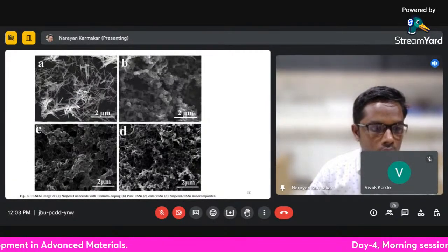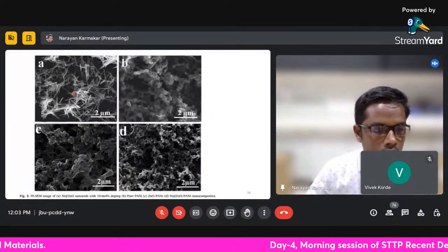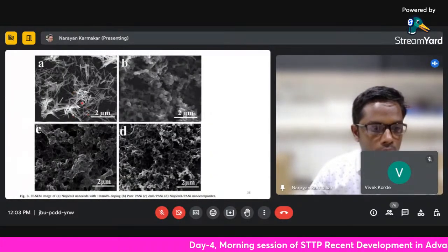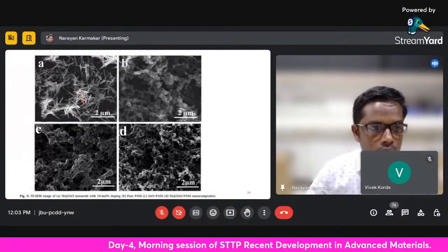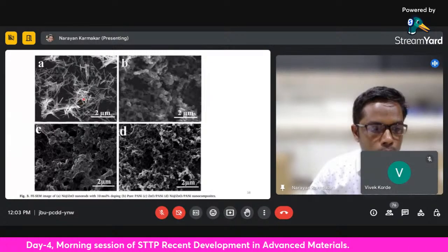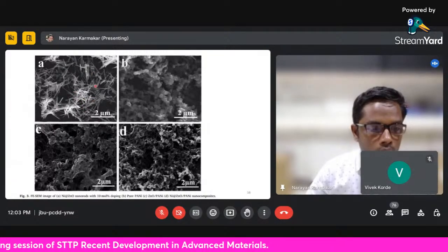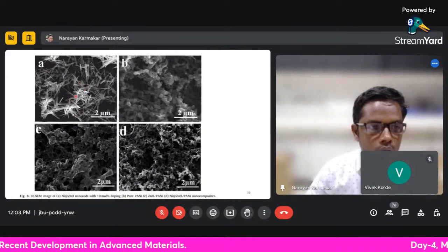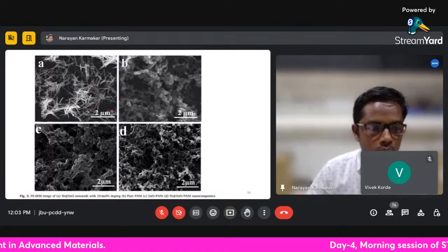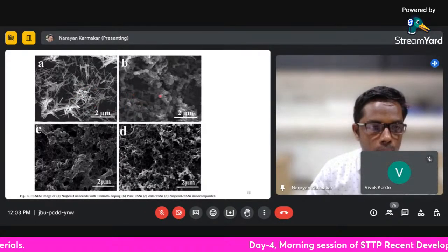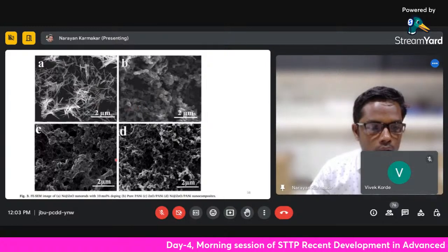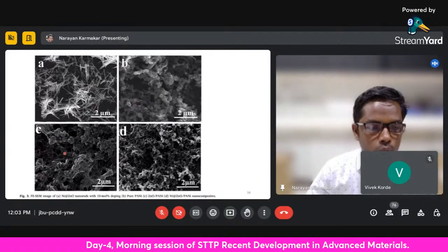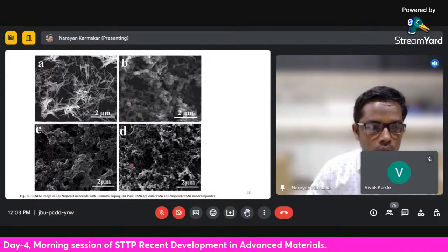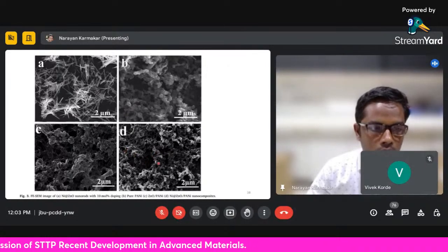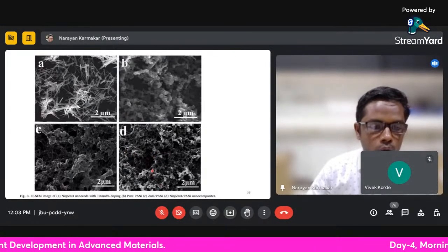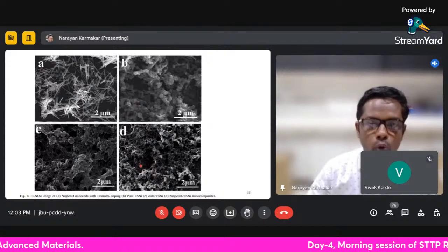So this is the image of this nickel-doped ZnO nanorods with 10 mol% doping, where you can see that the zinc oxide nanoparticles doped with nickel are clearly visible. This is the image of the pure Pani, this is the image of the zinc oxide doped with Pani, and this is the composite, where you can see that the nickel-doped ZnO-Pani nanocomposite shows a more porous structure.